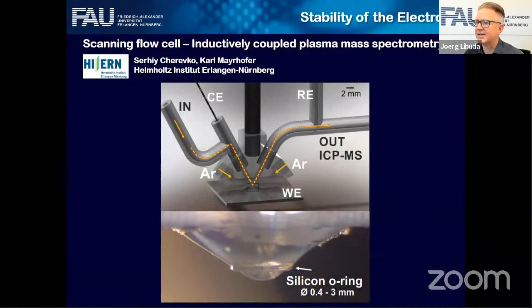Yeah, and the last mass spectrometry I want to mention is mass spectrometry that allows you to detect stability of single crystals. What we're using here together is the instrument developed and run by the group of Karl Mayrhofer at the Helmholtz Institute in Erlangen. They developed this scanning flow cell inductively coupled plasma mass spectrometry, where you have a flow of electrolyte and you detect with an ICP-MS the composition of the electrolyte, and then you can bring this cell in contact with a model surface, as I showed. And in this experiment, you can measure dissolution rate, and it's really unbelievable how sensitive this experiment is.